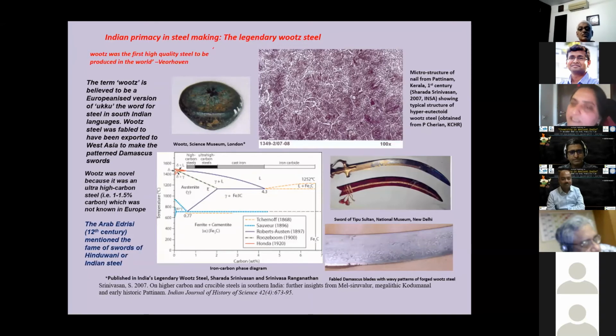Now, why that was really important is that when you forged it very extensively, you get this pattern of the alternating light cementite and the dark pearlite, which is a typical pattern of the Damascus blade. Now, the term Damascus, although it's thought to be really to do with Damascus, is not necessarily that. It actually derives from the Arabic term Damashq, which is this kind of pattern which you see on silk as well, which has this wavy pattern and so on. So anyway, these blades came to be known as Damascus blades.